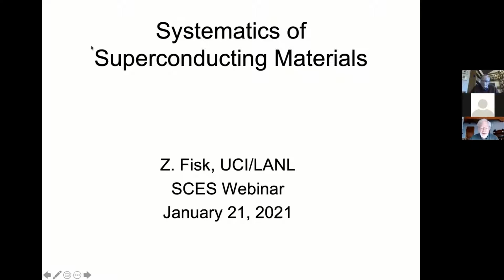In the mid-70s, Zachary's attention turned to intermetallic superconductors, where, among other things, he pointed out that this unusual saturation in their normal state resistivity corresponded to an electronic mean free path that's comparable to an interatomic spacing. And then in the 1980s, Zachary's work on heavy fermion superconductivity was interrupted by high TC. And even in that era, he was the first to discover high TC superconductivity coexisting with antiferromagnetic order in the rare earth barium-2-copper-3-O-7 system. And that discovery clearly pointed to the role of copper oxygen planes in producing the high TC.